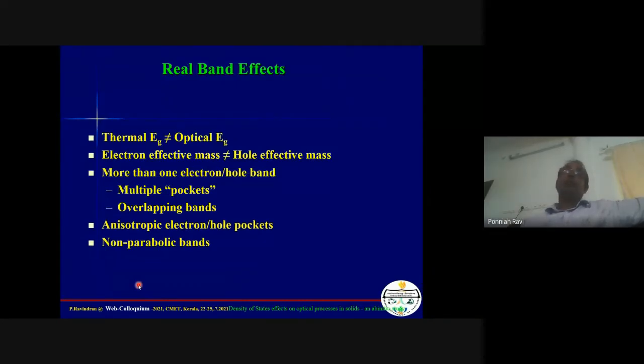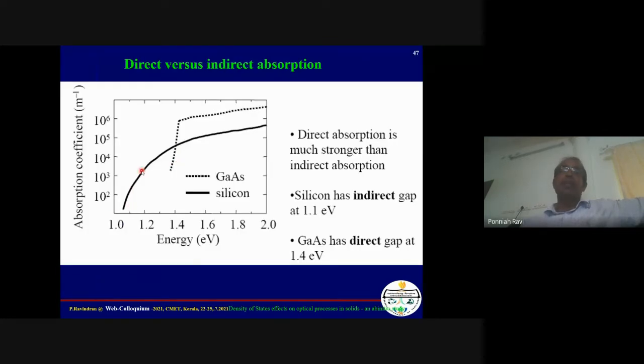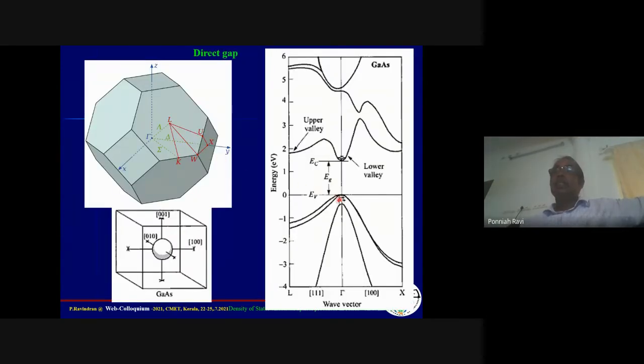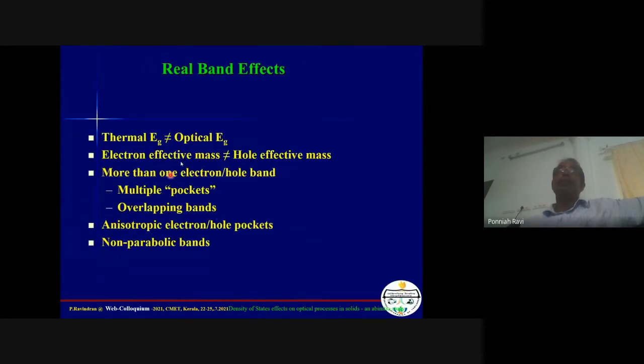We measure experimental band gap in different ways: thermal gap from temperature-dependent electrical conductivity, and optical gap from optical absorption measurements. For silicon, optical absorption starts around 1.1 eV; for gallium arsenide around 1.4 eV. These two types of gap can be different. The effective mass of electrons and holes also differ because the band slope is different at the valence band maxima and conduction band minima. The effective mass is derived from the second derivative of energy with respect to k.